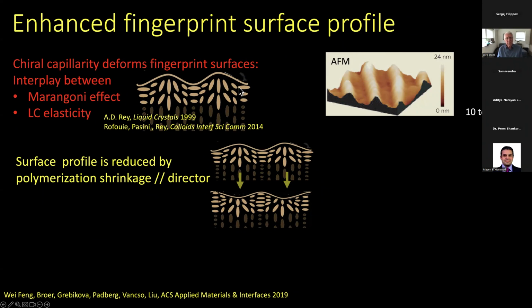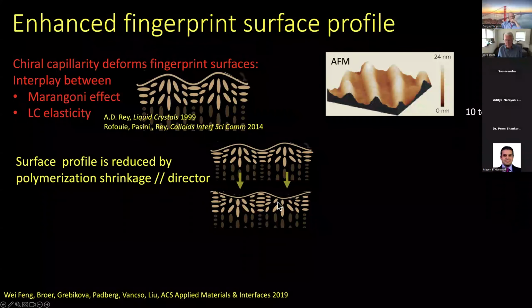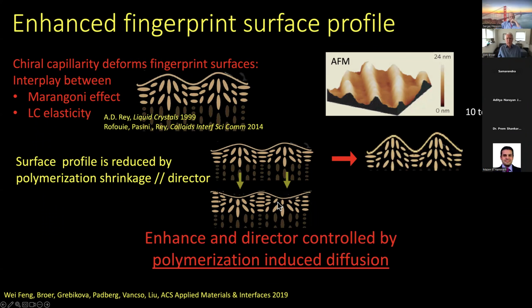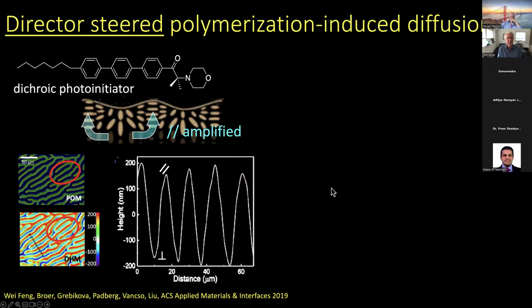However, if you start polymerizing, the polymerization shrinkage is higher parallel than perpendicular to the orientation. So basically you are counterbalancing the initial surface alignment, and you could even get a negative alignment. And this is not what you want. So we have to find a trick to come to a more initially higher oriented state. And for that, we developed the process of director-steered polymerization-induced diffusion.